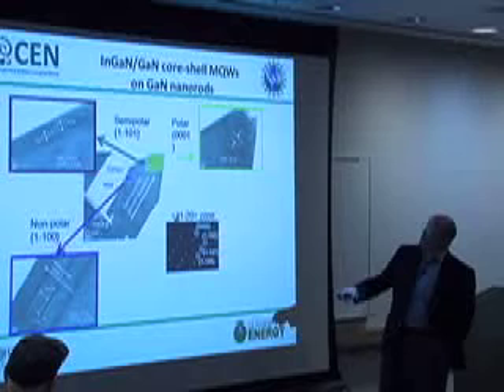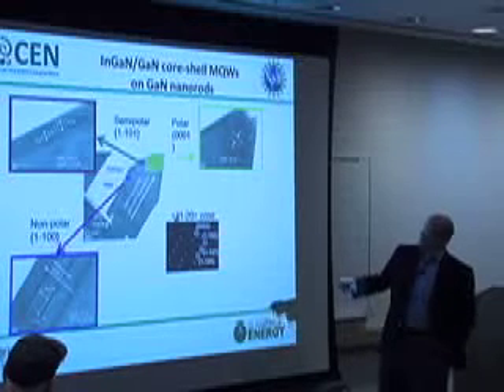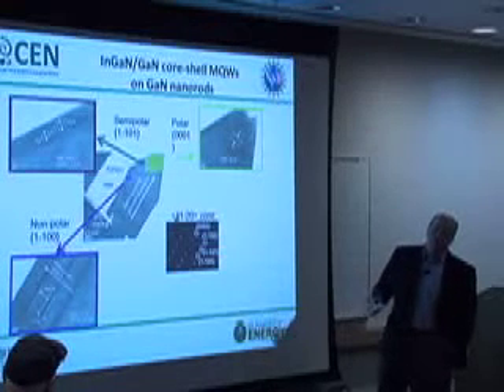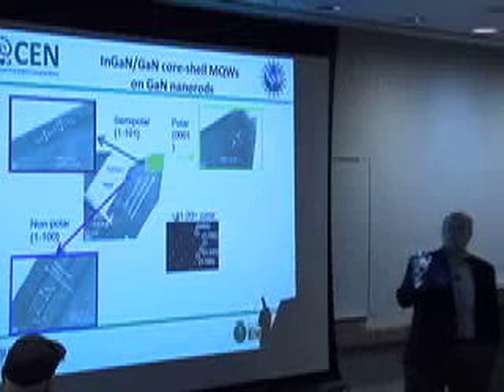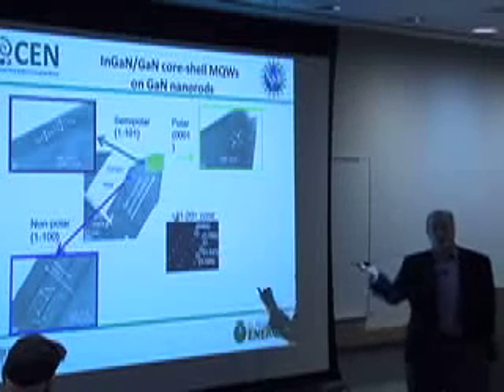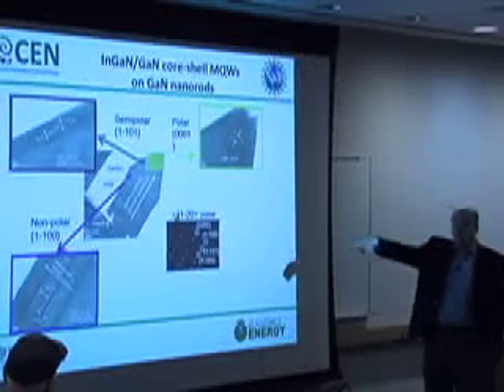We see no dislocations propagating from the substrate. We have only once encountered a dislocation in doing TEM, and that one bent over to the side.